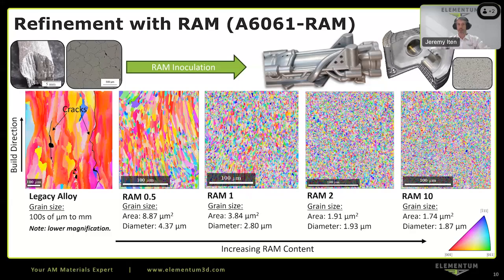Now you've eliminated that columnar texture, you've eliminated any cracking issues. You get a cross-sectional grain diameter, in this case, under 2 microns. So very fine microstructure with great properties. If you go to a RAM10, that's again a nominal 10 volume percent of the ceramic product phase. You don't get a lot of further refinement because it's pretty much fully refined by 2 volume percent, but you do continue to get increased strength, increased stiffness, wear resistance, and elevated temperature performance. So there may be reasons to go even higher, but with the RAM2, you're typically getting comparable or slightly improved properties compared to the wrought counterpart alloys.